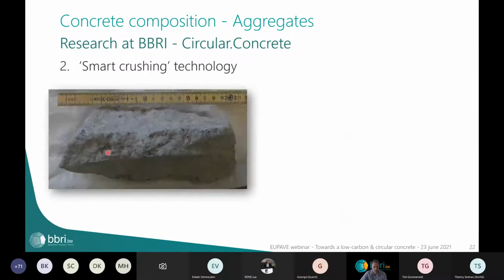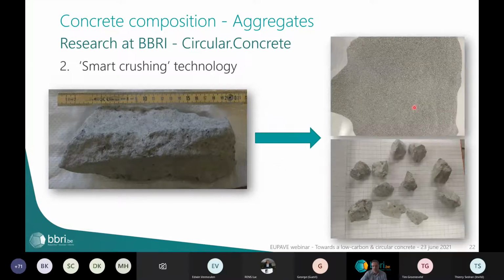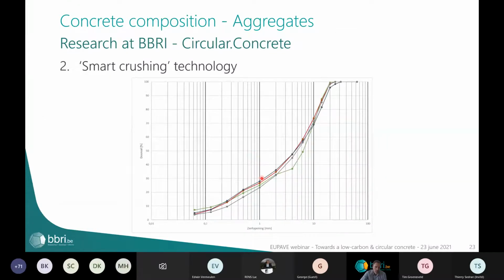So what we did was we sent some debris, which we received from different producers in Belgium. You can see there are large, very large debris fractions that we sent to Circulaire Mineral, and they returned us a combination of all different fractions all together, and we then sieved them into the different fractions. And we can see that we did this for 4 different origins of recycled concrete debris, and we saw that in fact all the returned samples showed a very similar aggregate size distribution, and also a lot of fines.